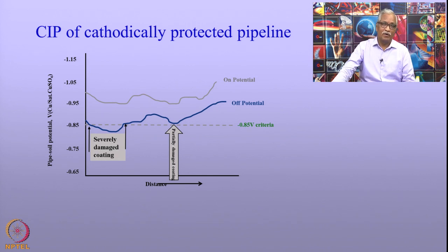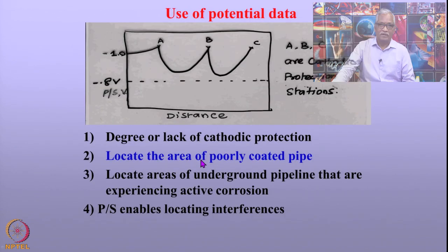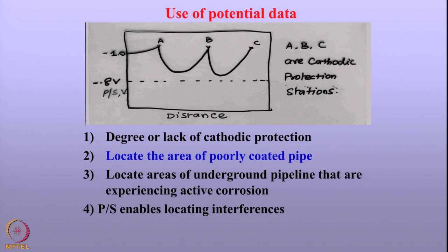As compared to CIP of the unprotected pipelines, for the cathodically protected pipelines the pipe to soil potential is very smooth. It does not have very severe variations with respect to distance. We have summarized here how the pipe to soil potential can vary with respect to distance between the various test stations, and A, B and C represent various cathodic protection stations here. And you can see here this line corresponds to the cathodic protection criterion of minus 0.85 volts. If the potential lies above this, then the pipeline is cathodically protected, and if the potential falls below this, the pipeline is not protected against corrosion sufficiently.